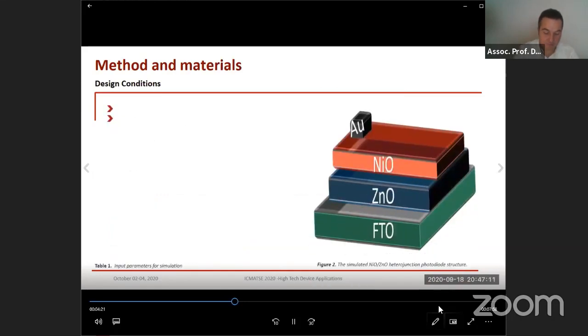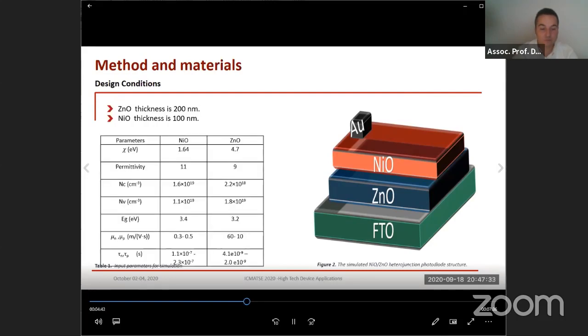The following structure describes the NiO/ZnO heterojunction photodetector. As you are seeing, we use gold and FTO as conducting layers. Considering that the zinc oxide thickness is 200 nanometers and the NiO thickness is 100 nanometers. In more detail, we have a parameters table.